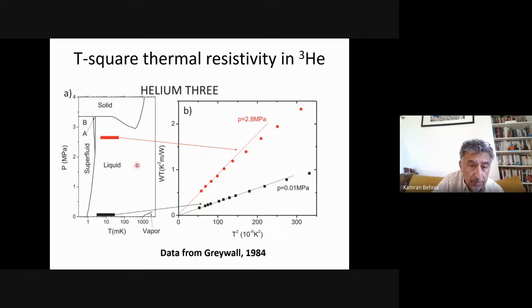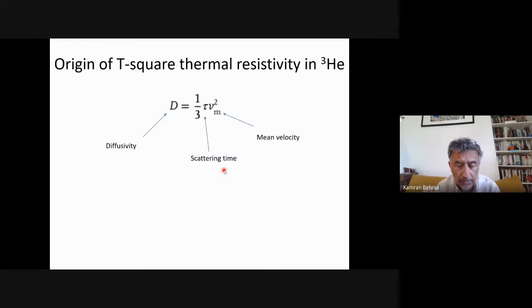You have also his data at this pressure. You see where correlations are much stronger. You are on the verge of solidification. And as you can see, he still has some T-square behavior on a more limited region compared to this one. So these are really low temperatures, and the slope has become larger. Okay, so of course, in 1984, this was analyzed and understood in the language of Fermi liquid and the Landau parameters associated with correlations. Now, let me tell you how people understand T-square thermal resistivity in helium-3.